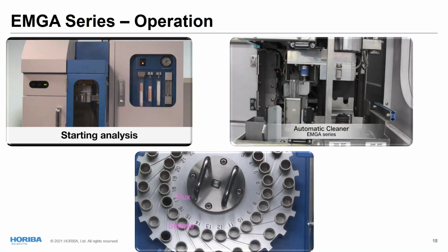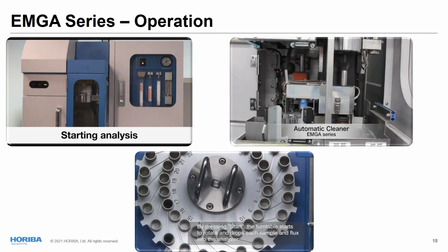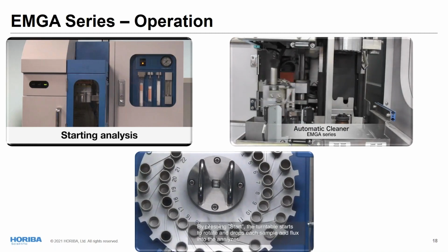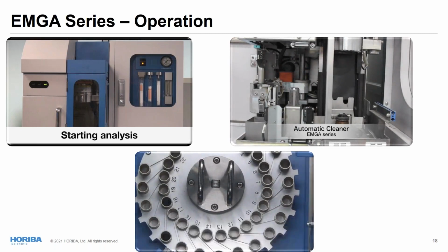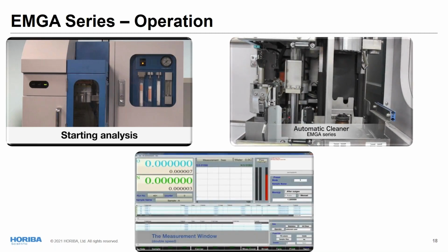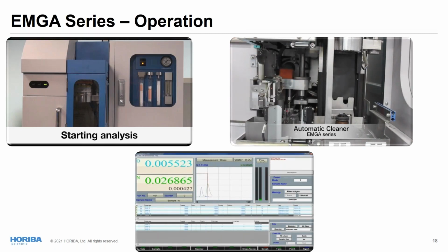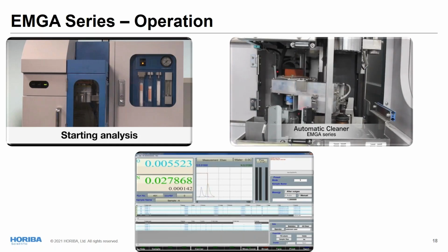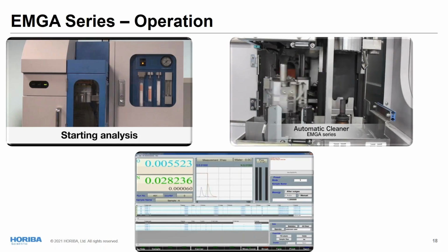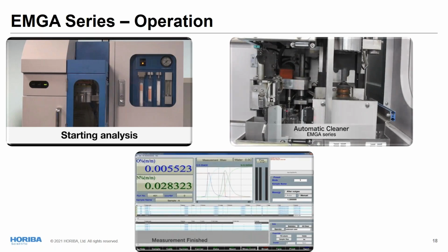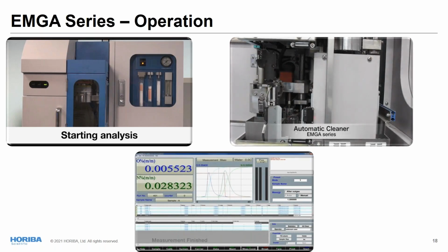You can see the flux and the sample that are dropped into the dual loading system. And from there, the analysis will start, outgassing steps. The sample will be introduced when needed. And the software will measure both, in that case, oxygen and nitrogen during the combustion. You can see here nitrogen and, oxygen, sorry. Oxygen at about 50 ppm and nitrogen at about 280 ppm.